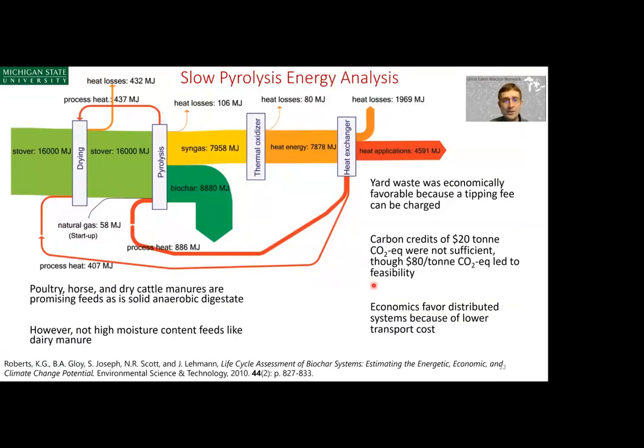The energy analysis of pyrolysis is also interesting. If we take corn stover, which is the leftover stalk and leaves of the corn plant after grain harvesting, and we take 1 metric ton and push it through this process of drying and pyrolysis, you can see of the 16,000 megajoules that goes in, more than half comes out as biochar under slow pyrolysis conditions. The rest goes with the vapor stream, which this group has elected to oxidize thermally, combust, to generate a hot gas, which is then run through a heat exchanger to transfer the heat and deliver it to heat applications, including to some extent the processes of drying and pyrolysis themselves.